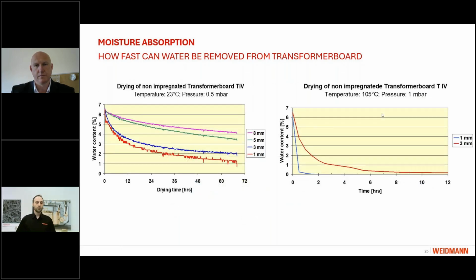Next, I want to highlight the importance of pressure. So if I want to not expose my material to heat, and I say, well, I will just reduce pressure to dry it, how beneficial and successful is this? You can see on both sides we have a quite low pressure of 0.5 and 1 millibar, but the left-hand side is at low temperatures while the right-hand side is at high temperatures. And we see that the 1 millimeter board at low temperatures takes hours to dry to roughly 1% water content, while when we have temperature and pressure, this doesn't take more than 1 hour.